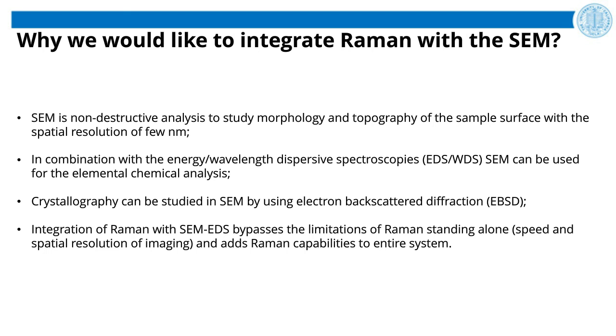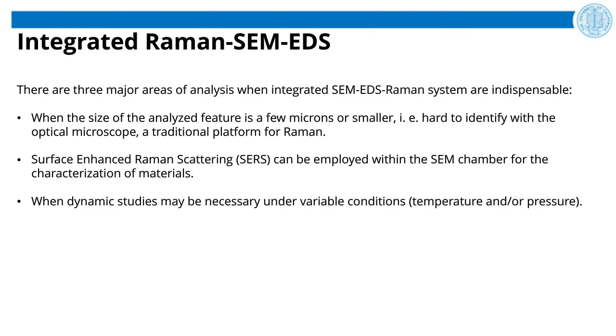Nevertheless, we can outline three major areas of analysis where integrated SEM-EDS-Raman systems are indispensable. First of all, when the size of the analyzed feature is a few microns or smaller, it is hard to identify the feature with an optical microscope, which is the traditional platform for Raman. Then, surface-enhanced Raman scattering can be employed within the SEM chamber for characterization of materials. And the third area is when dynamic studies may be necessary under variable conditions such as temperature and pressure. SEM temperature stages of different designs are currently commercially available, as well as alternating pressure systems through the use of variable pressure or environmental SEM, which are also available these days.